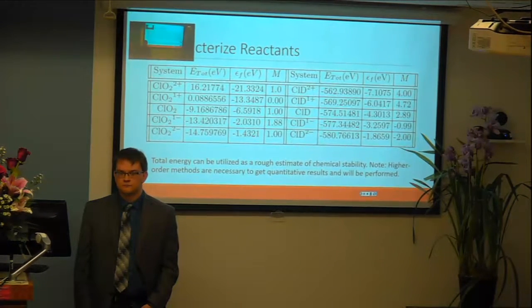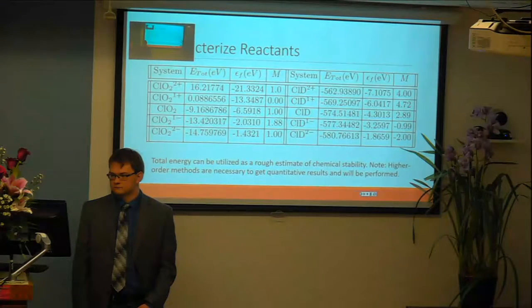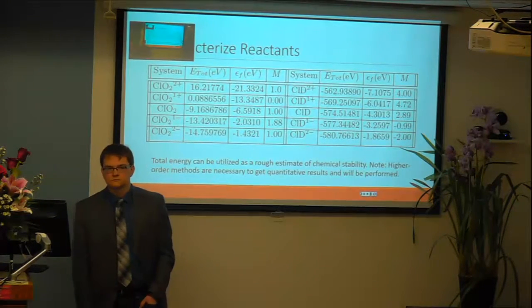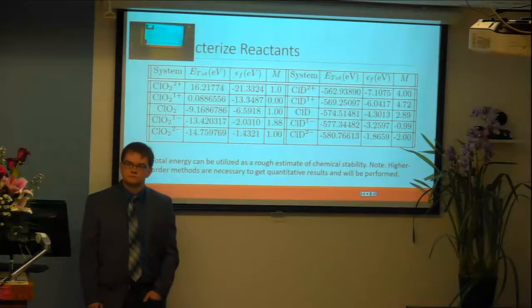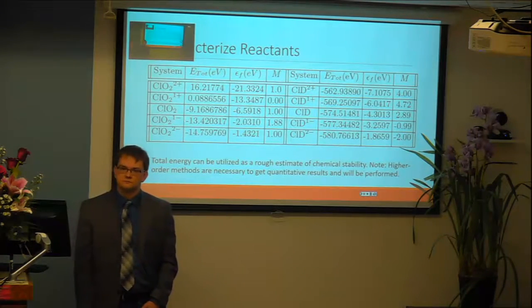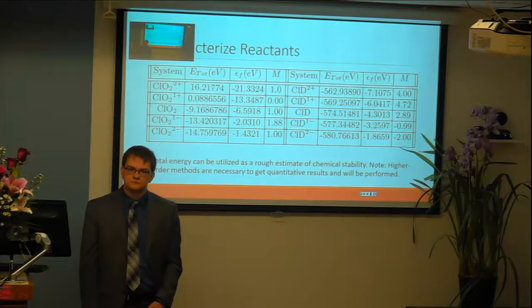And so this is not showing that the ClO2 minus is so stable. You can tell that because the number goes down a very small amount when you go from the -1 to the -2. It's not a very big amount when you go from the neutral to the -1, or from the +1 to the 0, or from the +2 to the +1. So you have a discount on how much the energy is.